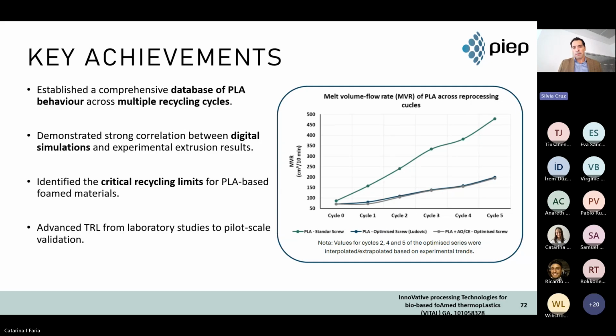And on the bottom, we see the evolution with, I would say, optimized screw configuration and parameters configuration. And as I mentioned before, we didn't get too much difference between the non-additivated and the additivated material. I think there is still some work to do on this level, but at least we get this comfortable correlation between the digital simulation and the experimental results. It was quite interesting because we know Ludovic was previously developed for fossil-based materials. We are using it for bio-based materials, but we get good correlations on that. And then, of course, we could identify some critical recycle limits on the PLA. And it was also quite important for the project.